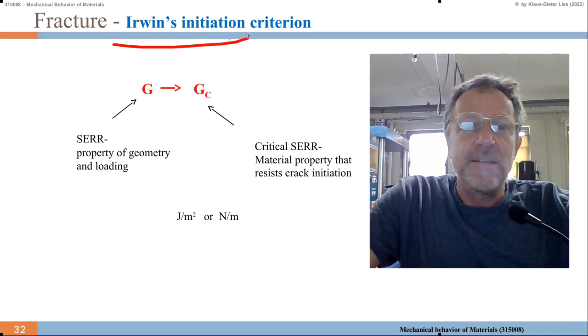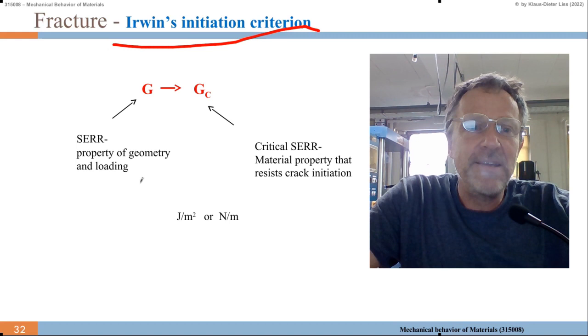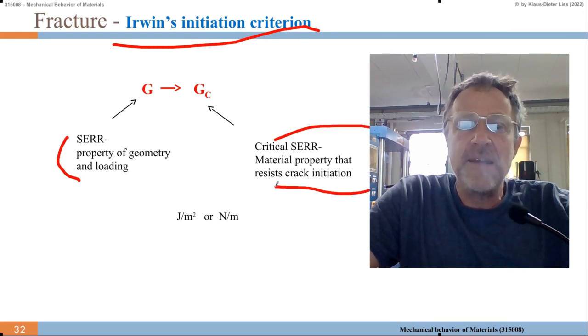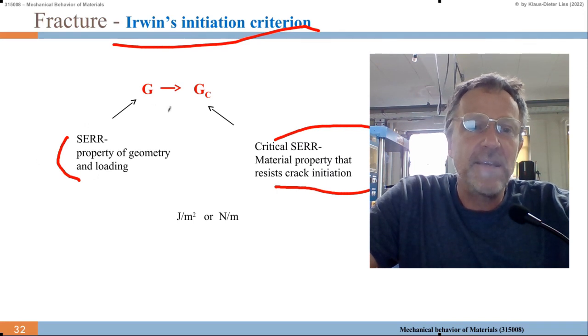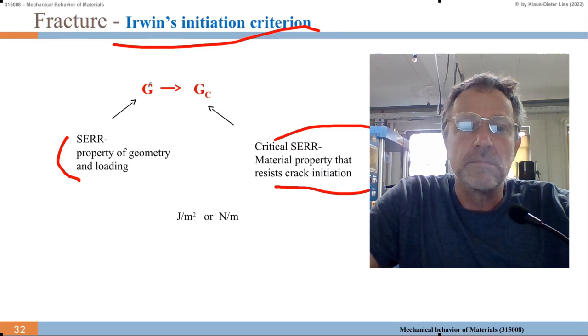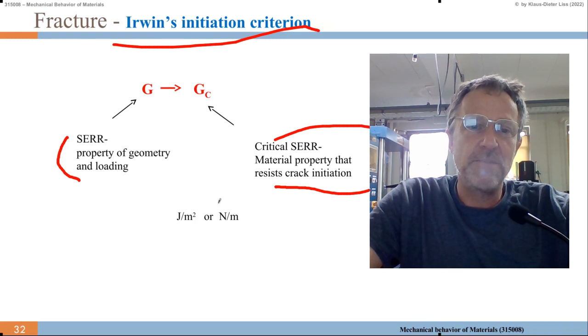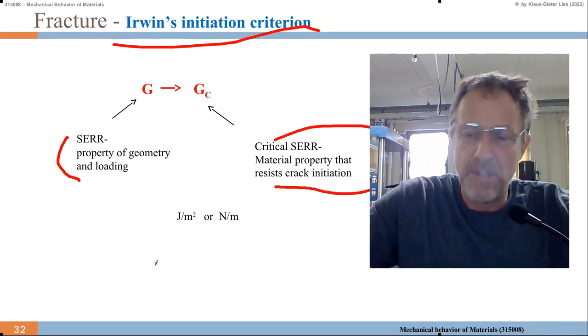So we have discussed Irwin's criterion for crack initiation. We have the strain energy release rate, G, which is a property of the geometry and the loading of the material. And then we have the critical G, which is the material property that resists crack initiation. So this is the material constant, and we have the geometric loading term, and then we have to compare them. The units are sometimes joule per square meter or Newton per meter, which are the same unit.